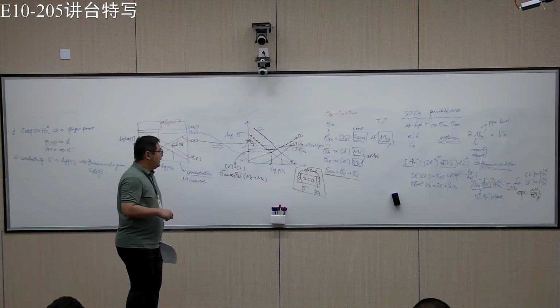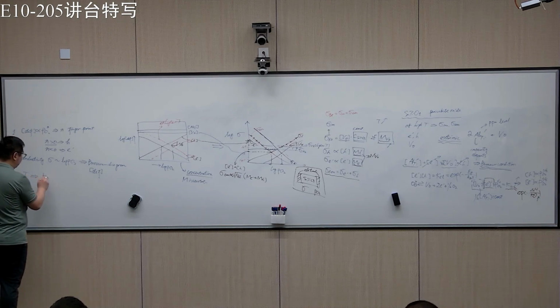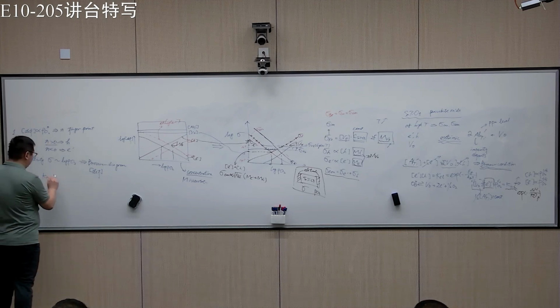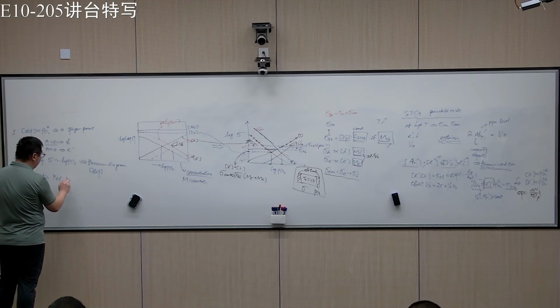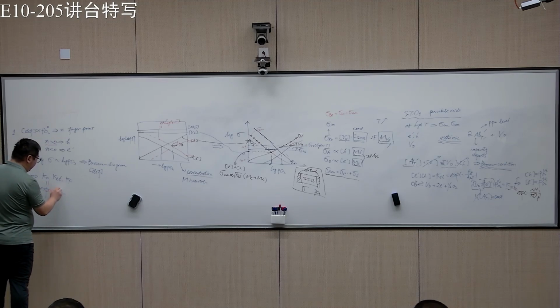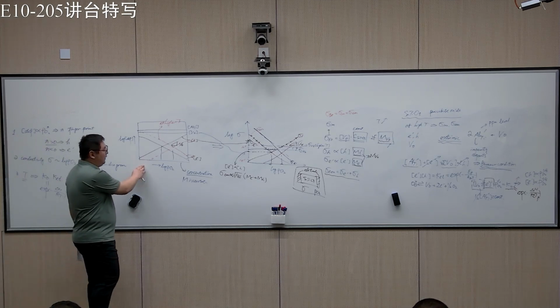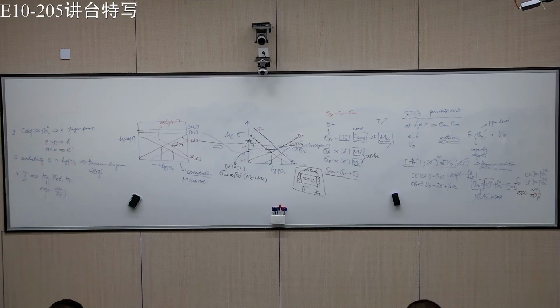The third thing is the temperature. If you change the temperature, you should think that it will change K_O, K_el, maybe K_F, because these are some kind of exponential. You can write delta H, or whatever thermodynamic quantity, over kT. If you change the temperature, you change that, and then you change the Brouwer diagram. So today we basically talked about two things.